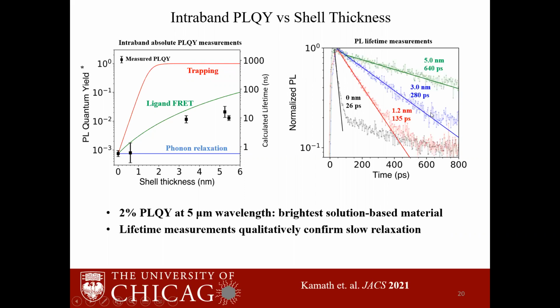We have also done lifetime measurements in collaboration with Chris. And here, we see an increase in the intraband lifetime, which further confirms that the increase in the quantum yield is due to a slowing of the non-radiative rate. And finally, by comparing the experimental trend to the 3 simulations, we see that the experimental data matches fairly well with the ligand FRET mechanism.